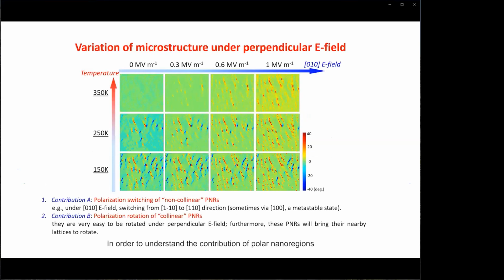In order to understand the contribution of polar nanoregions to the transverse dielectric response, the microstructure variation upon perpendicular electric field is given here. We can see that there are two contributions of polar nanoregions. For the non-collinear polar nanoregions, they will be switched from one stable state to another under electric field. At 150 Kelvin, lots of blue polar nanoregions will switch to red ones as a [010] electric field is applied. For the collinear polar nanoregions, we can see from the condition of 350 Kelvin that these polar nanoregions are easy to rotate and will bring the nearby lattice to rotate.